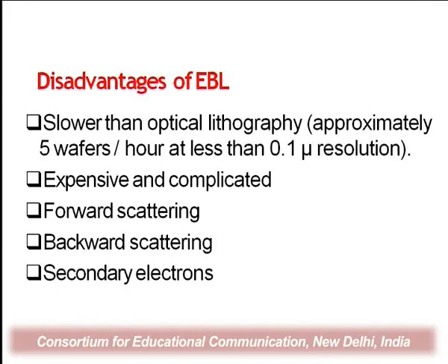It is much slower than optical lithography techniques. It takes time to prepare the devices. Approximately 5 wafers per hour can be prepared at less than 0.1 micron resolution. It is also very expensive and complicated.